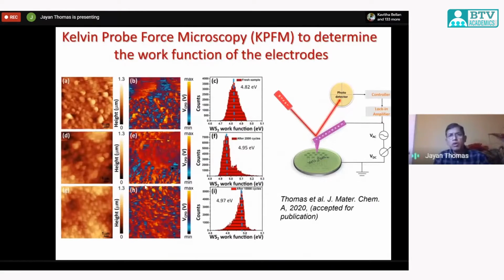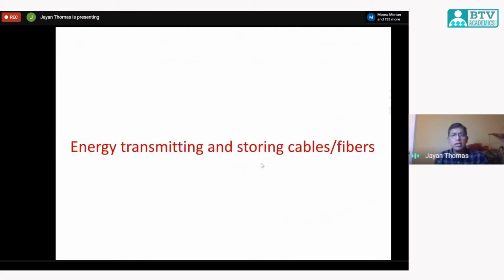So how do we measure this work function? Typically, we use Kelvin Probe Force Microscopy, which will give you the ideal work function that is going to be felt by the electrode in your supercapacitor. So we use the Kelvin probe method to measure the work function, and there is a recent paper just accepted on determining the work function of these electrodes using this KPFM method. But it does not detail more than that. There will be another paper coming up soon, which is going to deal with this type of modification and such things.